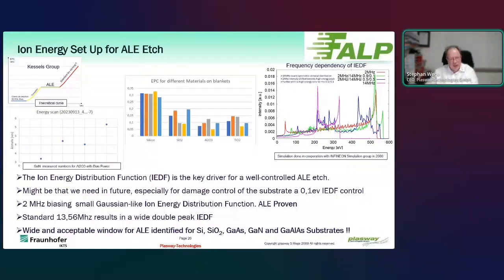The most important topic, besides bringing the gases and besides having a good and uniform plasma, is that your reactor is able to have a very tiny control of the ion energy. So when you look at some publications, especially from Kessels' group in Eindhoven, you find here the situation. First, you etch nothing because you have no ion energy, almost nothing. Then you have a transition region where you start to etch the first layer, and then you have a more or less flat area before you really come into a standard dry etch area.